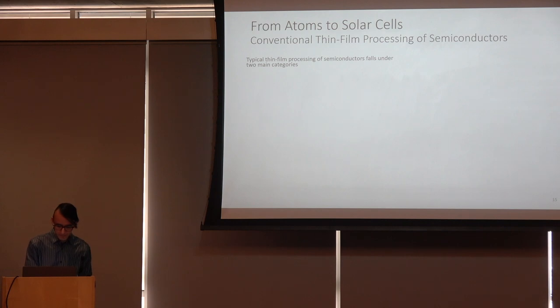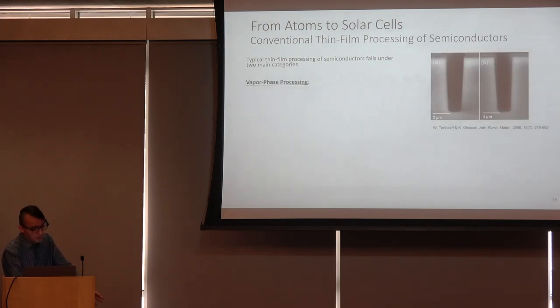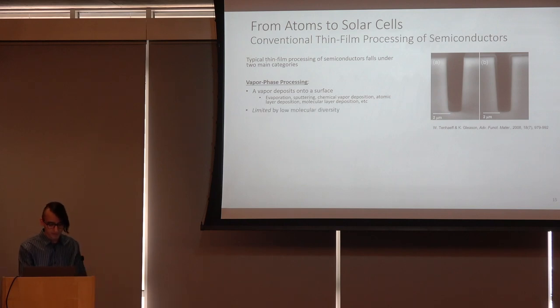Now, this takes us to conventional processing of semiconductors with a special focus on these conjugated polymers. So typical processing techniques fall under two categories. One would be vapor phase processing, where you have vapor of some material that then deposits on your surface, and this includes methods such as evaporation techniques, sputtering, chemical vapor deposition, atomic layer deposition, molecular layer deposition, etc. And these techniques are very powerful. You can get very nice and uniform layers, including in highly complex topography, depending on the technique that you use.